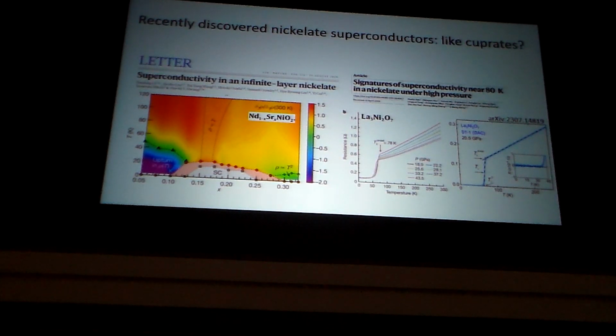Now, cuprates are not alone. Very recently, there have been some nickel oxide superconductors discovered. Those of you who know the periodic table, nickel is right next to copper. So you might expect that I could fool around with the valence of nickel and get something like the copper oxides. Well, that's in fact what these people here have done. They made a material. Of course, this is not a new idea. People tried to do this 30 years ago, but were unsuccessful because this is experimental physics. Sometimes making the materials you'd like to have is not so easy.